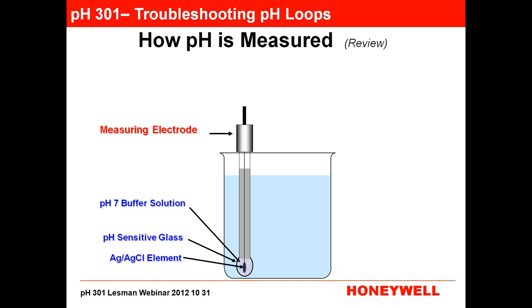So if you look at your pH sensor, you can see the components I was just speaking about. Your measuring electrode, you have a pH 7 buffer solution behind a pH sensitive glass that has all the active sites on it, and then your silver chloride wire. And this device changes voltage depending on the pH of the solution. At 7 pH, it has 0 millivolts because you have an approximately 7 pH buffered solution on the inside, 7 pH solution on the outside, so you don't have any voltage.